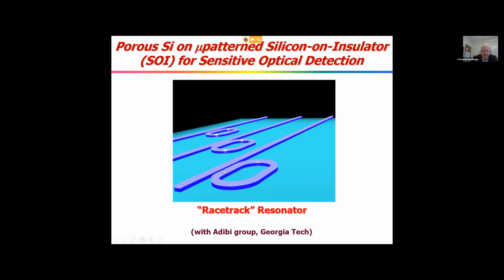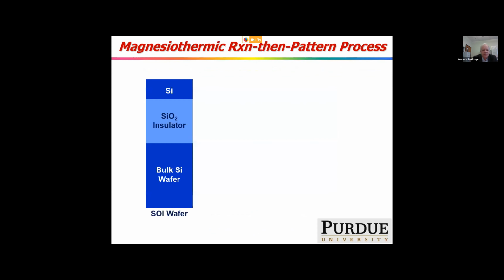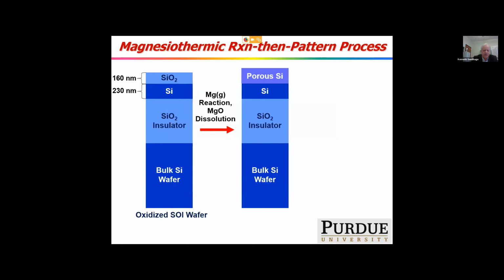and that happens at very particular wavelengths. So if you happen to have a porous silicon surface on a dense silicon racetrack or waveguide, that provides more surface area for an analyte to attach. And when the analyte does attach, that slightly alters the refractive index contrast, which shifts the wavelength at which this sudden reduction in transmission occurs. And so you can use it as a very sensitive detector. So we took silicon on insulator, silicon layer on silica on a bulk silicon wafer, partially oxidized that upper silicon, and then ran our magnesiothermic reaction to form ultimately porous silicon on dense silicon.